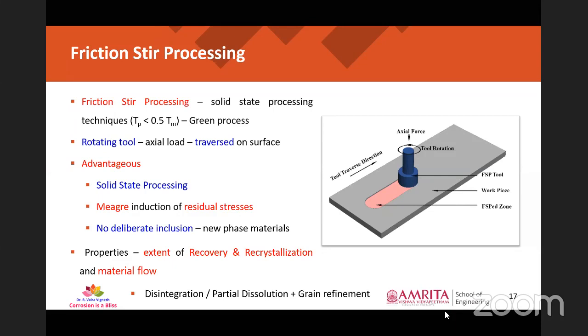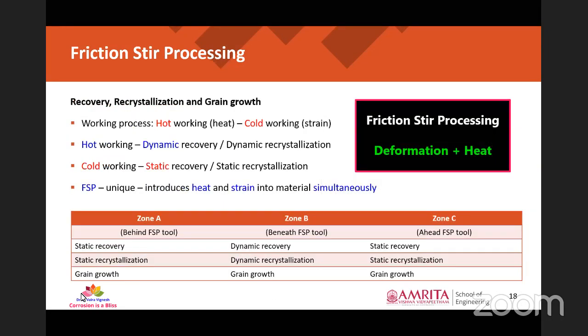So the disintegration and partial dissolution happens. Why? Because there is recovery and recrystallization phenomenon taking place in the material. Coming towards the recovery, recrystallization, and grain growth process in FSP, we can differentiate it into three zones. One is exactly beneath the FSP tool, that is going to be dynamic recovery, dynamic recrystallization, and grain growth. And the zones ahead and behind of the FSP tool will be subjected to static recovery, static recrystallization, and grain growth phenomenon.